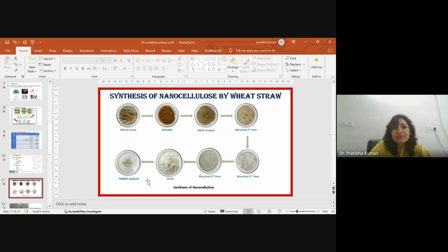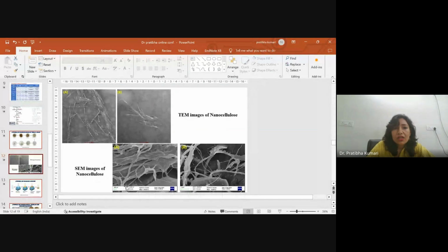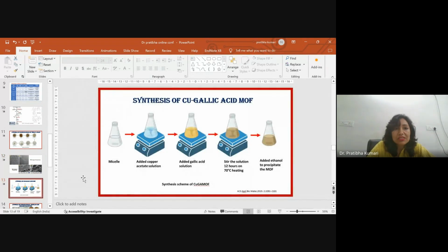So in this figure, we can see different stages of the cellulose. Like this is the wheat straw. When we grind it, it looks like this. Alkali treatment. Then we perform the bleaching. We dried it, and then in the last there is the TEMPO oxidized cellulose. So we'll get the cellulose like this. And from the TEM image and from the SEM images, you can see that the nanocellulose has a fibrous type of structure. So we isolated and we prepared this nanocellulose material.